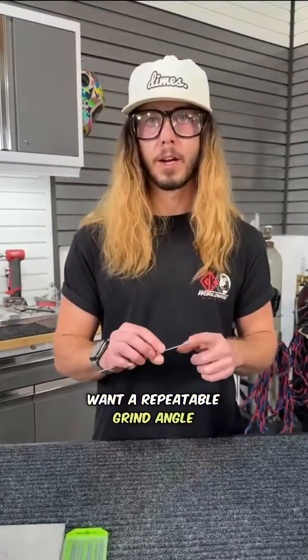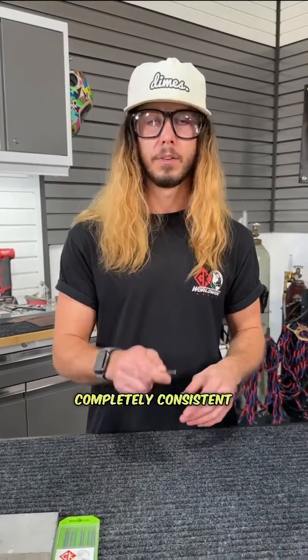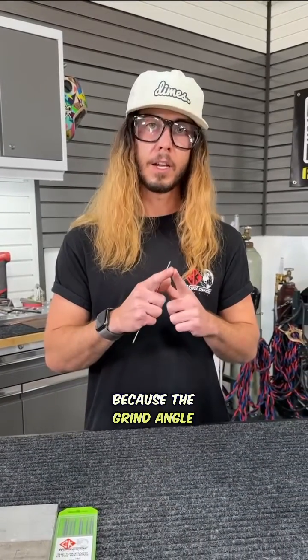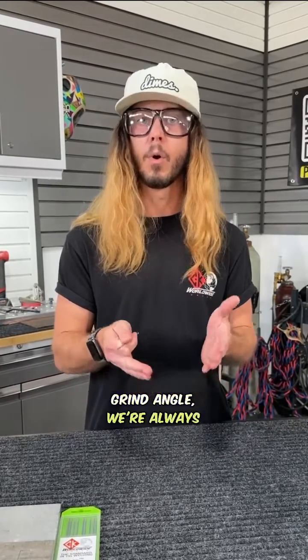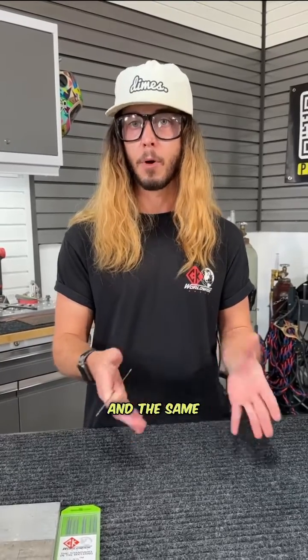I want a repeatable grind angle on here, something that's completely consistent from electrode to electrode, because the grind angle that we put on the electrode changes the arc shape and penetration profile. So if we have all of our tungstens at the same grind angle, we're always going to be delivering the same penetration and the same arc.